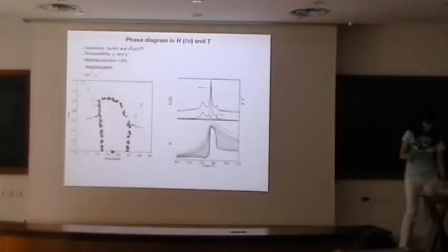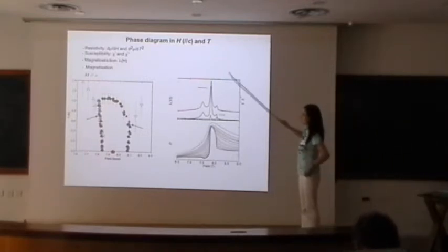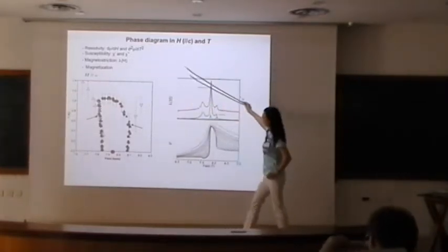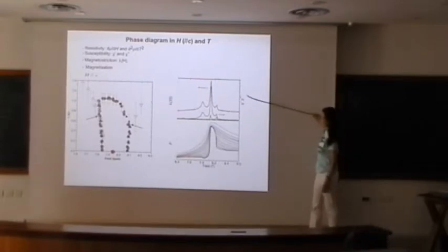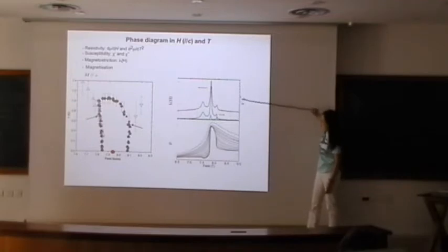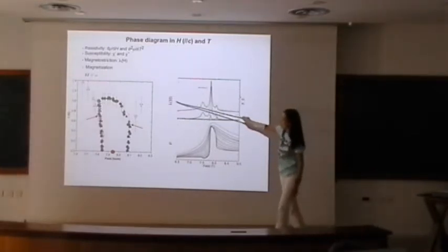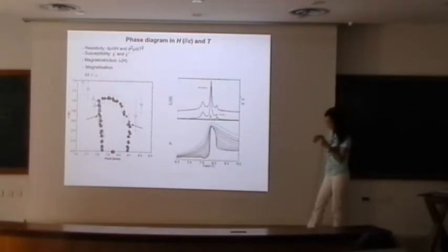Yeah, in fact, because of time, I have deleted a lot of things here, and there were some questions about that. So here, the measurements that have been done: susceptibility has been done, the real part, the imaginary part. There's interesting data at low field, which I don't think people know well enough. Here is the imaginary part of susceptibility, and this is the real part of susceptibility. We use some small AC frequency. And then magnetostriction, basically how the lattice constant changes as a function of magnetic field.